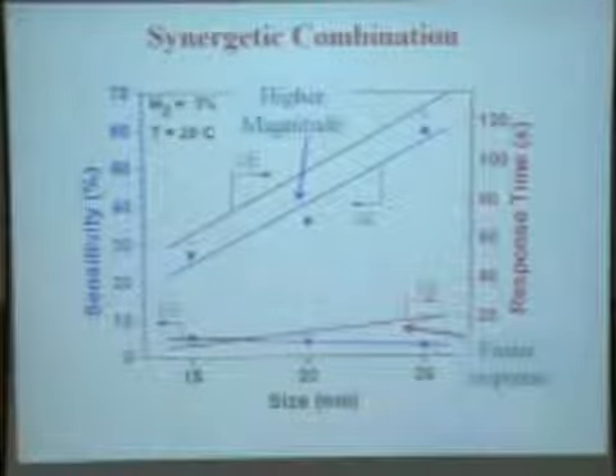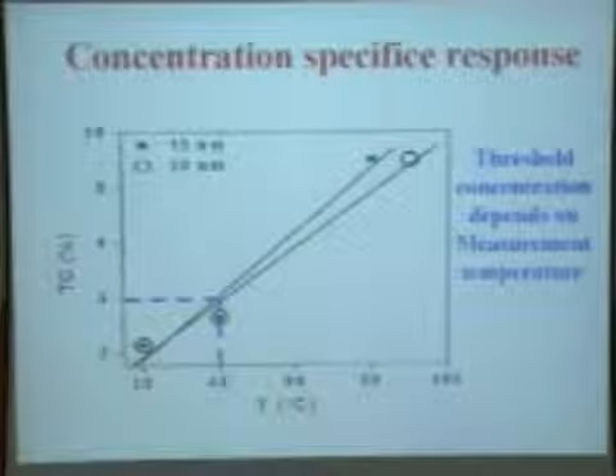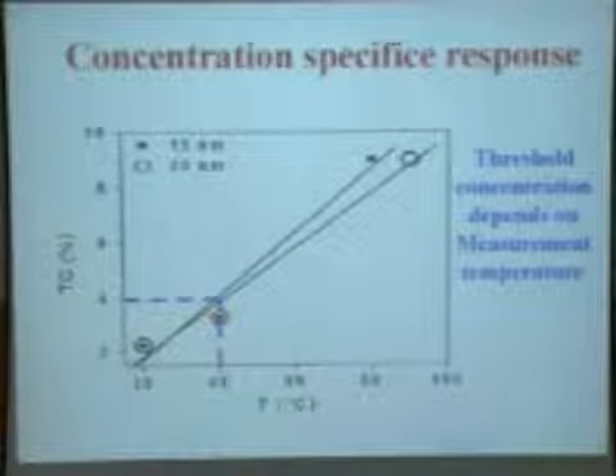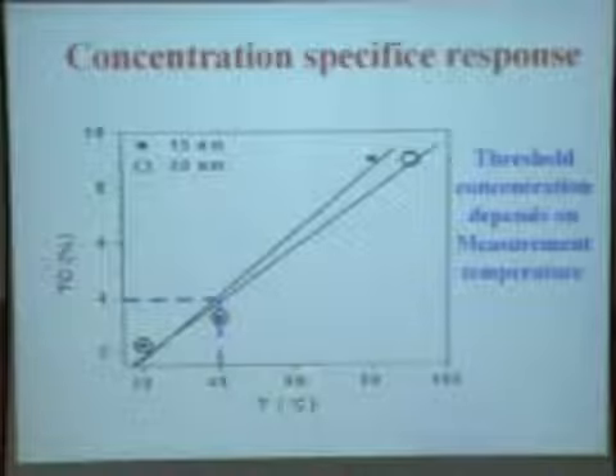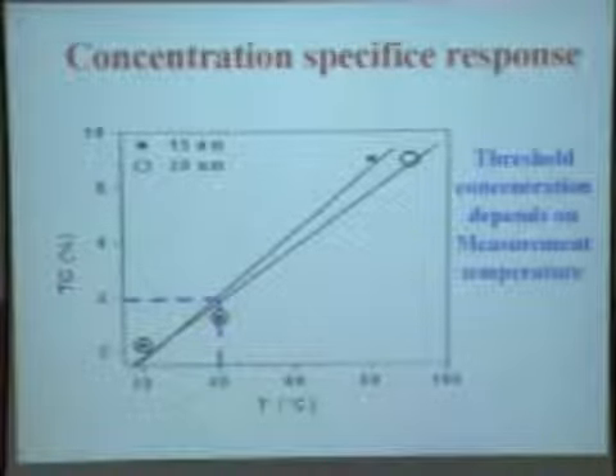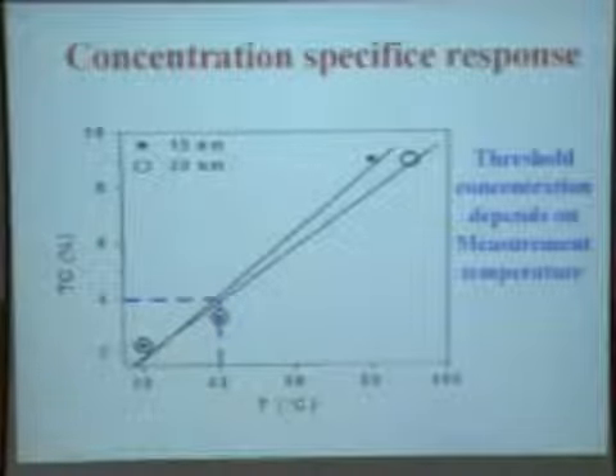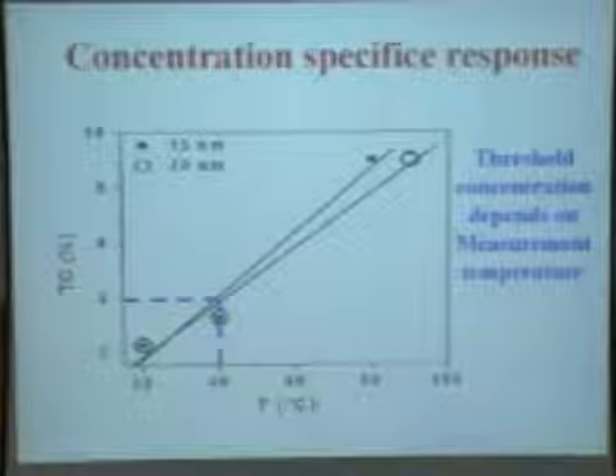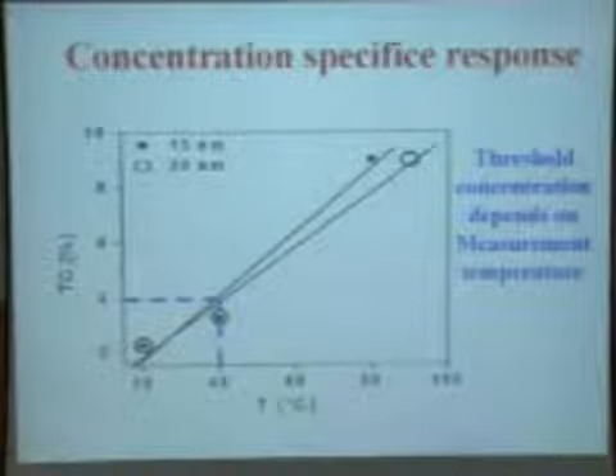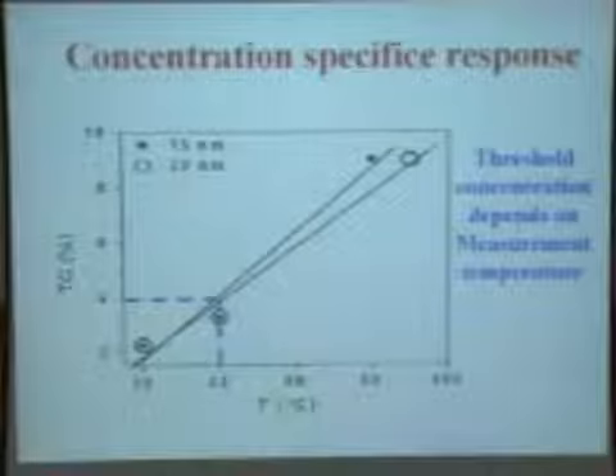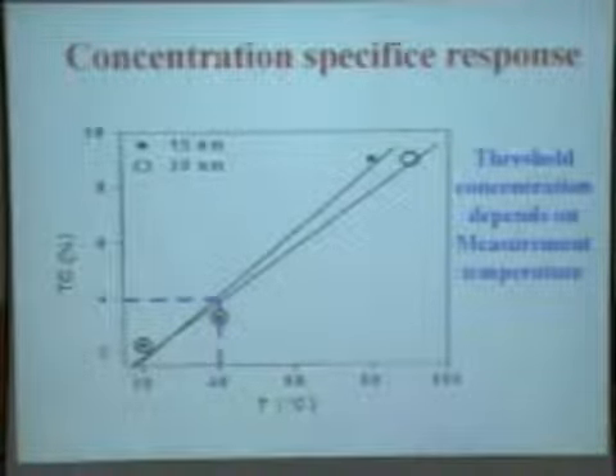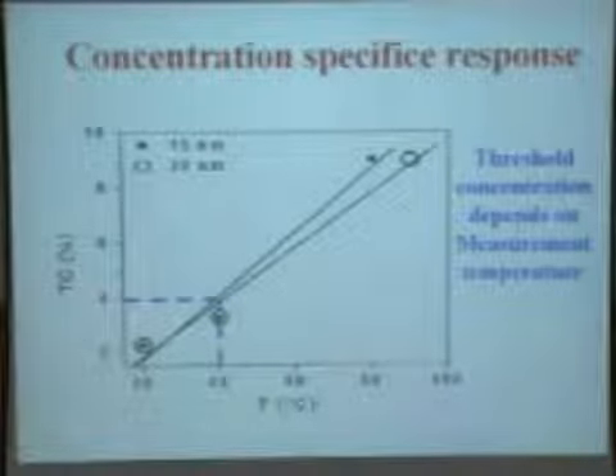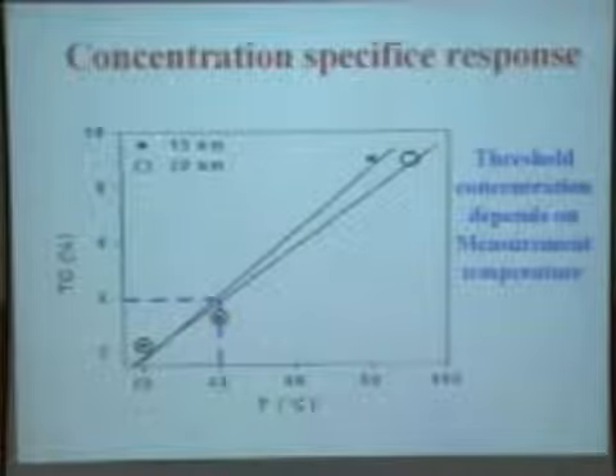I will not go into the detail, but what is important is that there is a threshold concentration at any temperature below which the response is slow saturation, and this threshold concentration depends upon the temperature. So depending upon what concentration of hydrogen one wants to measure, you can keep the sensor at a particular temperature and measure the response, and you can detect not only hydrogen but also get an idea of the concentration of hydrogen. For example, if the measurement temperature is 40 degrees centigrade, at 4% hydrogen the response changes from slow saturation to pulse-like. So you can measure 4% hydrogen, which is very important because it is the explosive limit for hydrogen. That kind of sensor can be made.